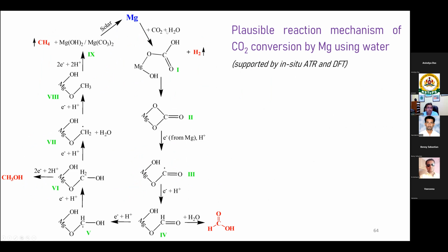Magnesium reacts with CO2 and water together. If CO2 is absent or if water is absent, the reaction doesn't happen. It has to be together. It forms basic magnesium carbonate, then takes electrons from magnesium and protons from water, keeps adding electron and proton, you get formic acid, adding more you get methanol, keep adding and you get methane. Obviously the selectivity of the reaction is towards methane, it doesn't really produce large amounts of acidic formic acid or methanol.